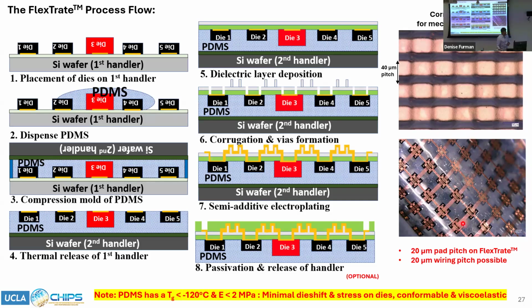So here you see a large scale system on a full 100 millimeter wafer, which consists of, I think, around a 30 by 30 array of around 900 dies, 1 millimeter square dies, that are interconnected at less than 20 micron interconnect pitch.